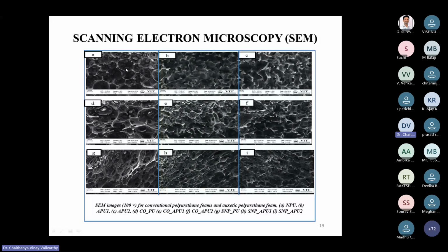These are the normal foams. We have seen that when we stretch the foam, because we are keeping the foam inside the container, these pores are completely accumulated with the ribs. We call these ribs in the cells. These ribs go completely inside the pores, which undergo buckling. So when we take out the foam and stretch it externally, these voids are completely filled with the ribs.